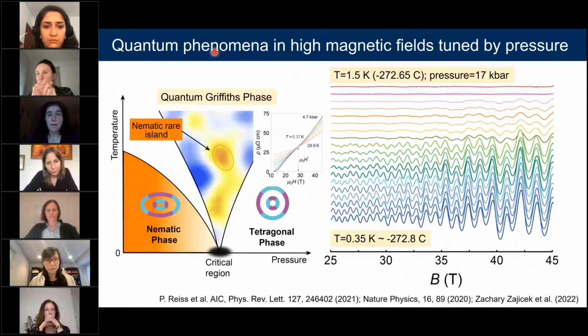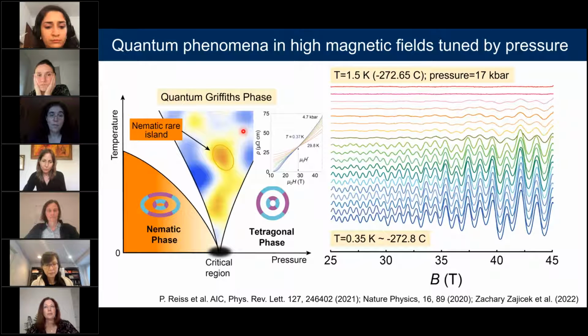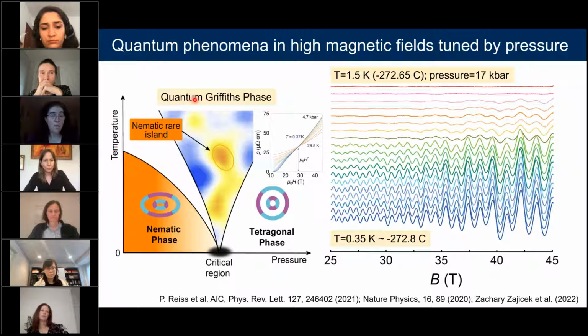Among the recent experiments which show how we can access quantum phenomena under extreme conditions tuned by pressure, these are quantum oscillations on the right. It shows how the amplitude of these oscillations is strongly temperature dependent, and they can only be observed at extremely low temperature, close to outer space temperatures, so close to 0.3 Kelvin. With this type of technique, we can also explore the nature of quantum critical phases. With applied pressure, we can tune, for example, the nematic electronic phase towards a critical regime. And recently we detected the formation of quantum Griffiths phases and very rare nematic islands appearing in the vicinity of this critical regime.